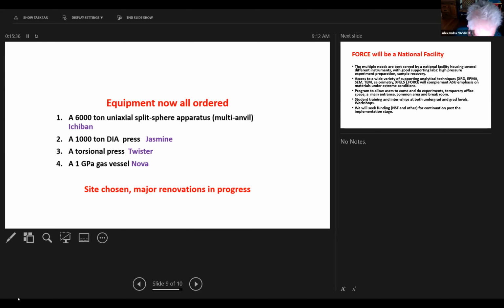So a DIA press that can go up to not quite the megabar range, but perhaps 0.8 of a megabar. Larger samples at lower pressure, smaller samples at higher pressure. And this is going to be the exploratory press for really very high pressure research.